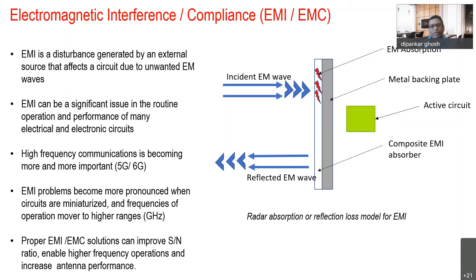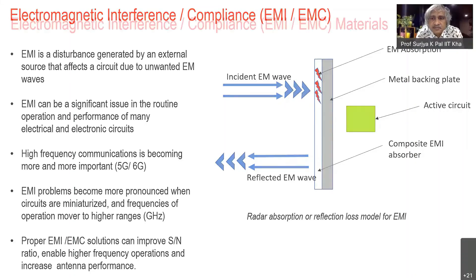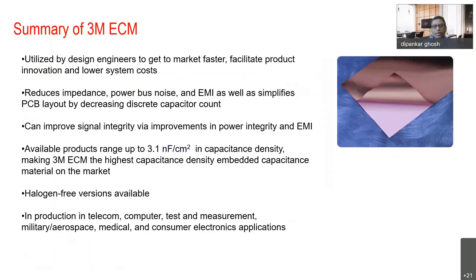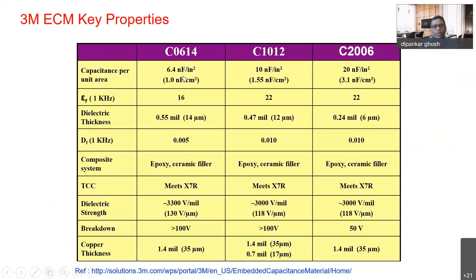What are the optimization challenges in embedded capacitor design? Quite a few. Customers always look for higher and higher capacitance per unit area. Currently our highest product is 3.1 nanofarad per centimeter squared — one of the highest in the industry. Higher capacitance value allows more miniaturization. But that is not the only thing — for example, the TCC values, the temperature coefficient of capacitance, should be as low as possible.